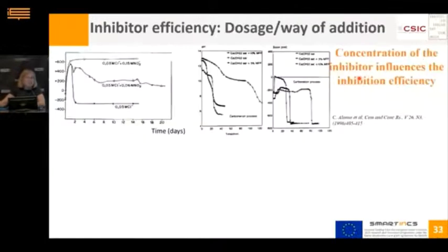But what about the inhibition efficiency? Let us see the case of nitrites. When they are added, they are not in the system. This is a poor solution containing chlorides, and a certain content of inhibitor is added. Progressively, the protection of the reinforcement is detected until the optimum amount is reached, and then the rebar is completely protected. The same will happen in the case with monofluorophosphate.